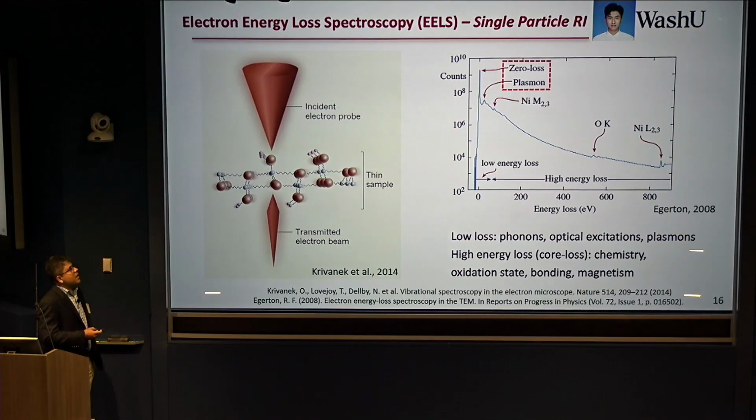This was Rohan Mishra's student, Jian, at Oak Ridge National Lab using their state-of-the-art microscope. In STEM electron microscopy, you look at the inelastic scattering by the electrons as they pass through the sample. In the low loss region, which is less than 50 eV, that gives you information on the phonon and optical excitation, plasmon, whereas greater than 50 eV, whatever spectra you get of the loss, you get information on the oxidation state, bonding mechanism, and chemistry.